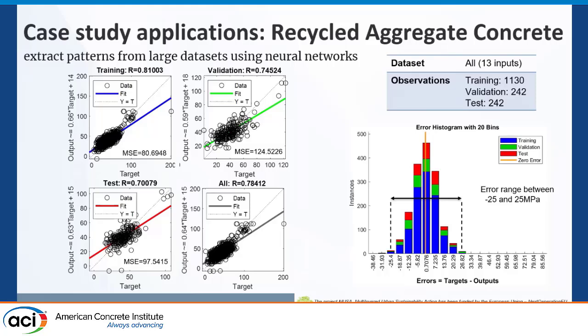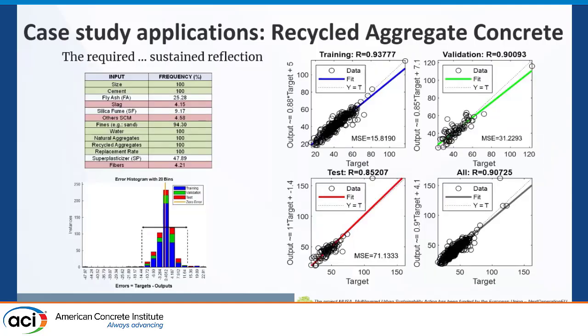So in the end, that is what AI does: extract patterns from large data sets, but then there was time for sustained reflection. The student came to me and said, well, I have these results. Then you have to sit down and look into that. Sustained reflection. And I asked her, look at the frequency of your data in the mix designs. So we realized that there were very few papers which had slag or other supplementary cementitious material different from fly ash, or had fibers. These very low frequency papers actually jeopardized the database.